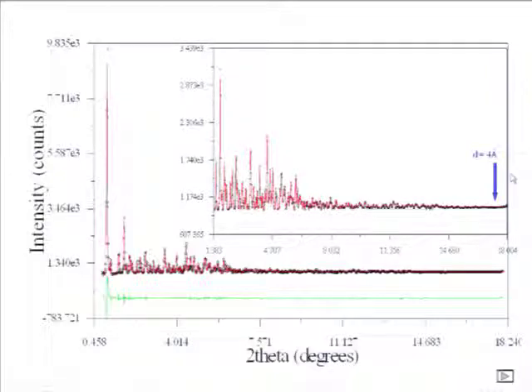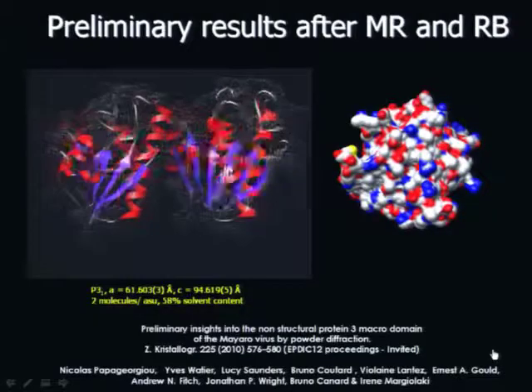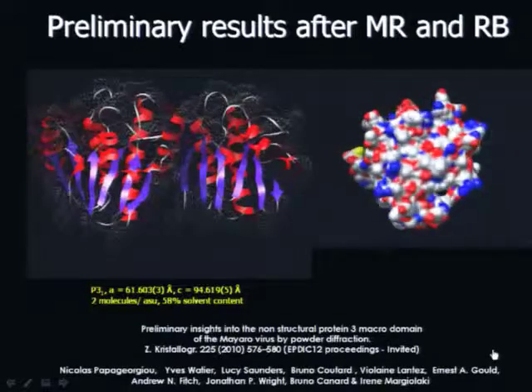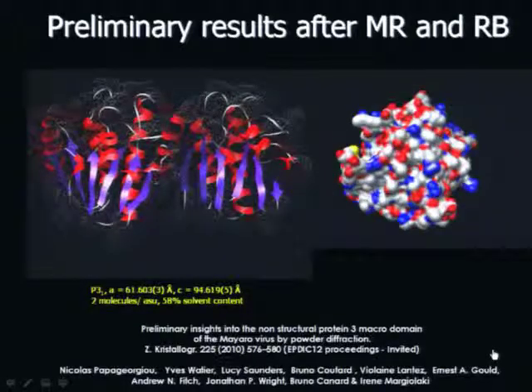And despite the fact that the form factor decays and the data decay, and here the information content is much less, again, based on this data, we got a first preliminary model from molecular replacement, and here you see the two molecules in the asymmetric unit and how each molecule looks like. This domain is important because it has this active site and it can accept ligands such as ADP, and that's why we think it can be used for producing new drugs against Mayaro virus.